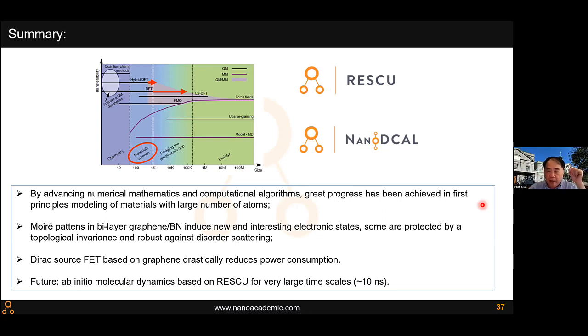But if you want to calculate phonon transport, there are well-established tools. And in our tool, we can calculate all the phonon properties, and then you will have to solve this Boltzmann transport equation for phonons. There are well-established tools in the literature, or even companies which produce those tools. They need the phonon dispersion, and then solve the distribution function for phonons in a classical approach. So that can be done.